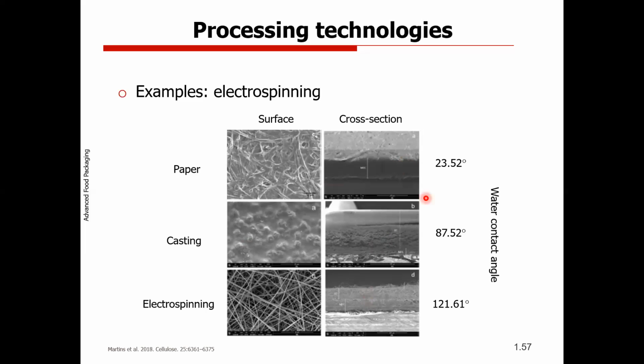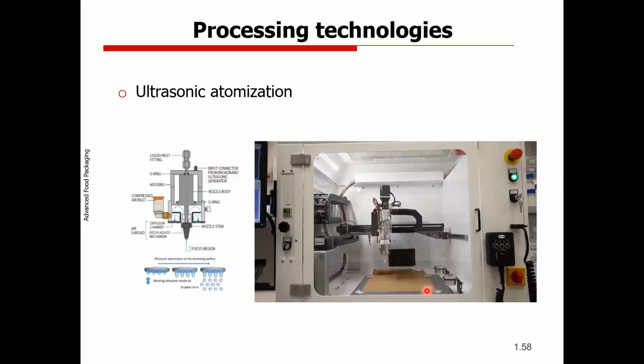And in this particular case, with casting we already increased it a lot. That's based on this kind of material that we used. But then with the production of the fibers, we are able to go through 120 degrees of water contact angle. That is a very hydrophobic material in this case. So this is one of the examples of use of electrospinning.